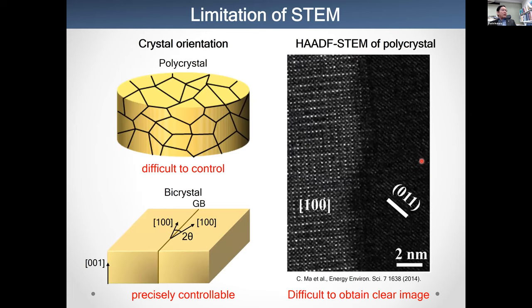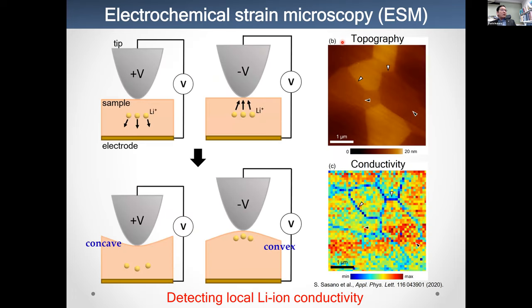If we look at the grain boundaries in a polycrystalline material, it's very difficult to determine the atomic structures, because one of the grains, for example, may be along the zone axis, but usually the other is inclined. Therefore, we fabricate a bicrystal, a well-defined sample, to precisely control the misorientation angle and grain boundary plane. I'm going to explain how to make the bicrystal later. And we also applied electrochemical strain microscopy.